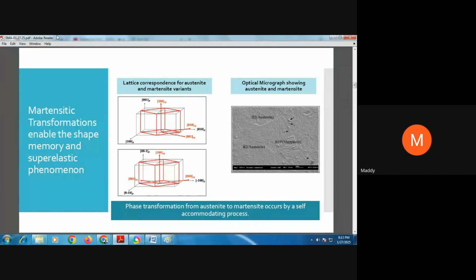Now, there are different variants of martensite, which enables the material to self-accommodate. That is the reason why you're able to see a phase transformation where there is no external change in shape, despite there being a phase change. How do we identify this? If you look at the optical micrograph on the right, you can see grains identified as austenite and martensite. Typically, austenite would look like any other grain structure, whereas in martensite you can see streaks of parallel lines, which is nothing but the twinning happening in martensite. So this is how you can identify it using an optical microscope. Next slide, please.